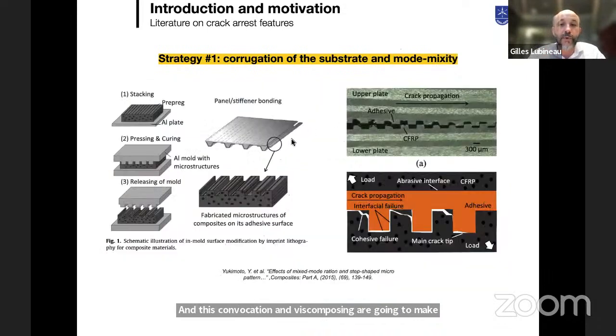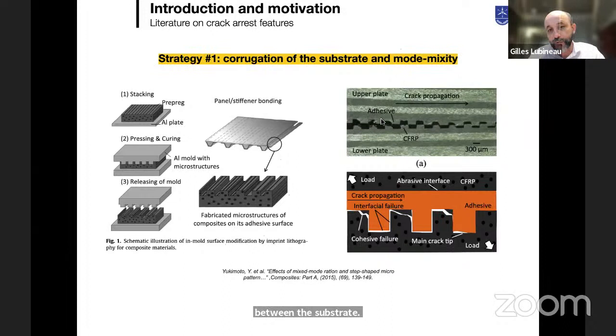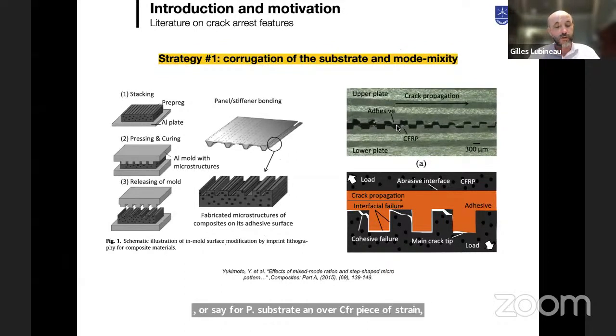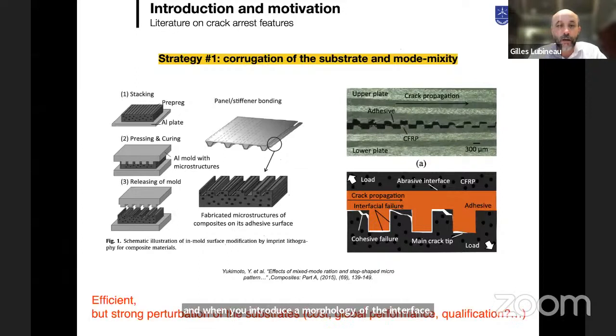Other strategies are based on introducing real interlock between the substrates. So here, for example, you have a composite substrate, a CFRP substrate, another CFRP substrate, and then you introduce a morphology of the interface that is going to, here again, fight the delamination. This is efficient, but this results, of course, in a very strong modification of the substrate and of the global performance of the system.